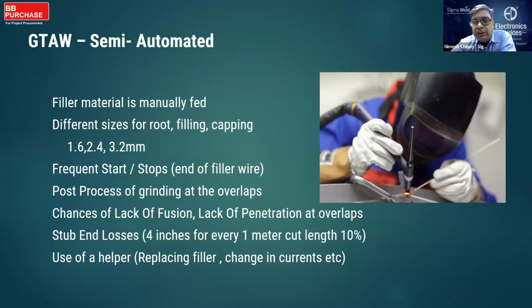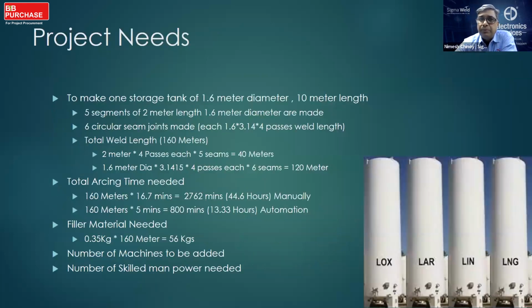You have stub-end losses. That means for every 1 meter cut length, you lose about 100 millimeters or 10 centimeters because the operator cannot reach the arc that far. And therefore, that's 10% of your cost of consumable throughout the project. And also, you need a helper to replace the filler wires or change the currents.